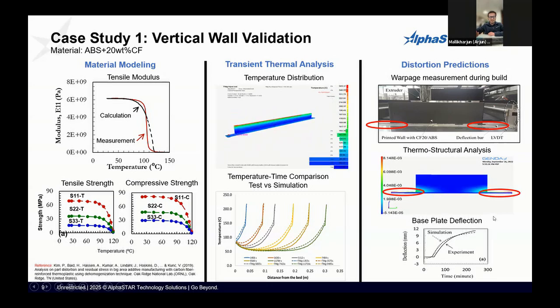So again, for any analysis, we start from the material side, because if we don't have the right material properties, no matter how perfect we design the simulation, it'll never give us the right response. So for that, going from left to right, we have the material modeling. As Sarat mentioned earlier, we use two different analyses. The one is cure kinetics to come up with the temperature dependent modulus. For anisotropic, this is a carbon fill system, ABS with 20% carbon fiber in it, so capturing all directions E11, E22, E33. Once we have the temperature dependent modulus completed, we go to the next step where we use the multi-factor technique to predict all the strength properties, which is shown on the left-hand side bottom.